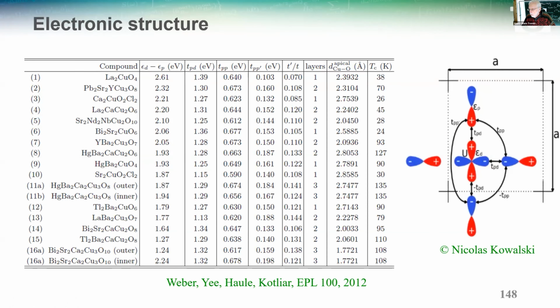You're not going to look at all the numbers in this table. Again, it comes from some work at Rutgers. The point is that electronic structure calculation gives us values for these hopping parameters, TPD, TPP, all of them, and also for epsilon P minus epsilon D. And if you look at TC, the maximum TC, it varies wildly between all these compounds.